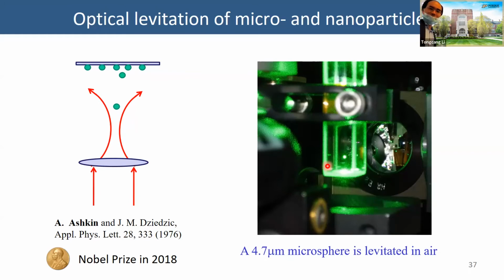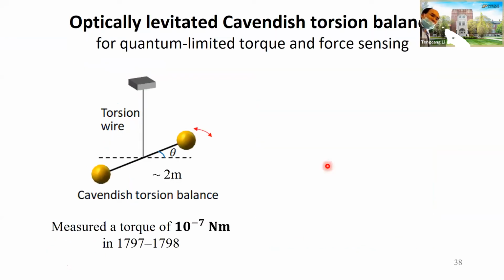The purpose of this, there are many things to do. I'm just focused on one thing, that's my work at Purdue. Basically, we want to create a so-called optically levitated Cavendish torsion balance for quantum-limited torque and force sensing. The original Cavendish torsion balance is formed by two balls suspended by a wire, and if you have a torque, the orientation will change. This was done more than 200 years ago. It measured a remarkably small torque, as small as 10 to the minus 7 newton meter, due to gravitational interaction, and this work determined the gravitational constant G.